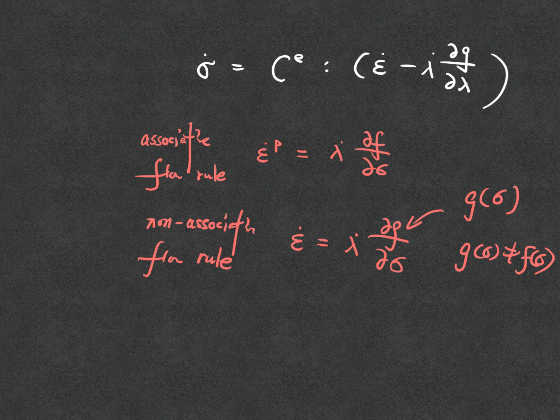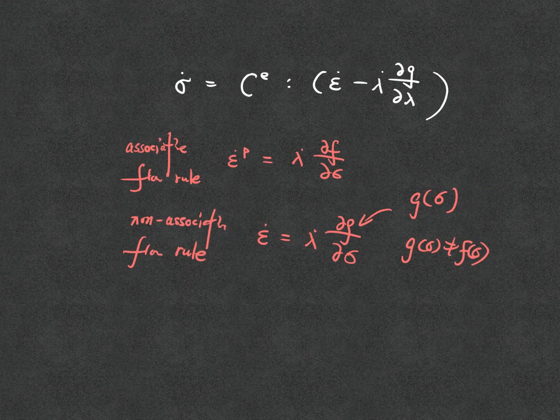There is no pressure mode. So you cannot model plastic dilatancy or plastic contraction, which means it doesn't work for soil in general. It can work in an undrained state where the water is trapped, so that approximately the entire material is incompressible. But it is a very common thing people use just for simplicity.